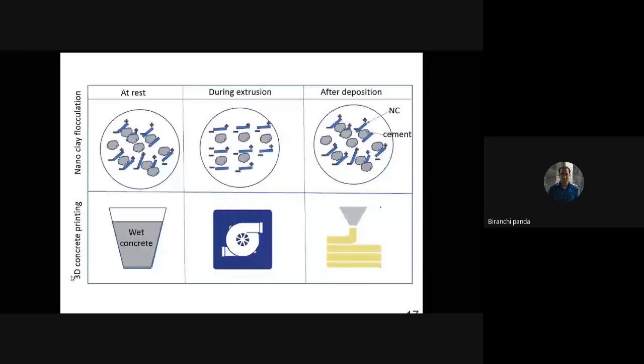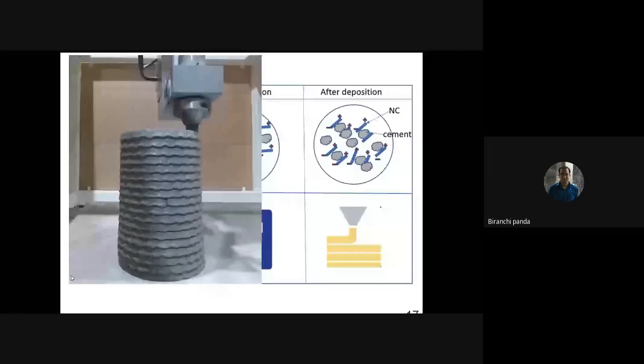During pumping, we need the material to have low viscosity, but after pumping, we need the same material to behave with high viscosity. How is it possible? We have to make it possible for printing of cement or concrete based material. So that was the main challenge while developing the material. But as I mentioned, with the help of nanomaterials, we were able to print more layers without any deformation.